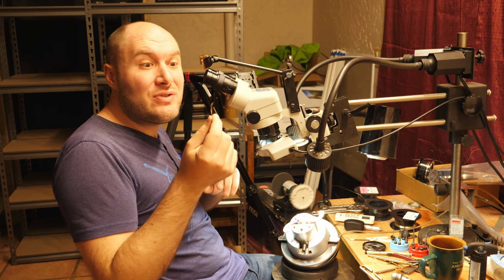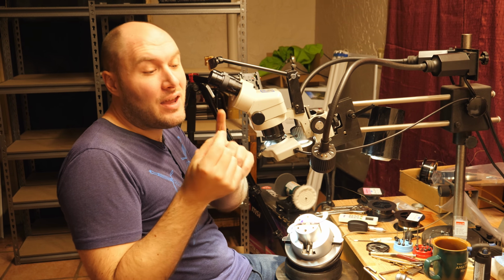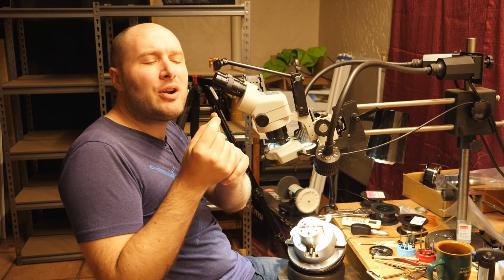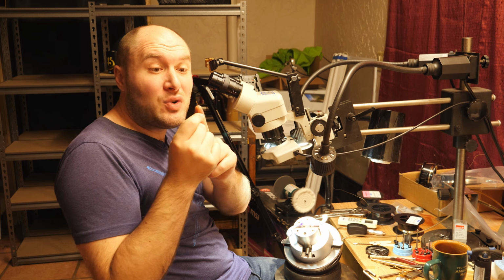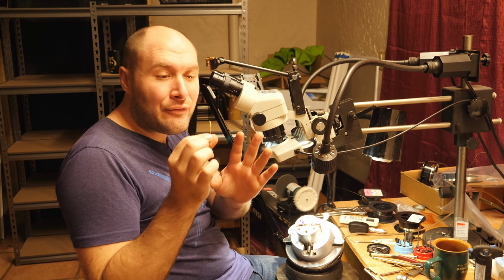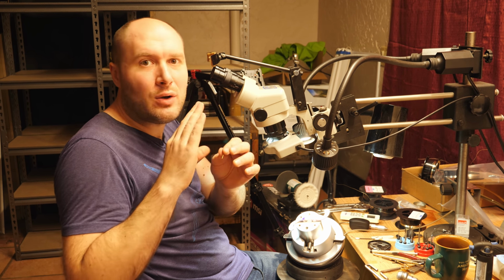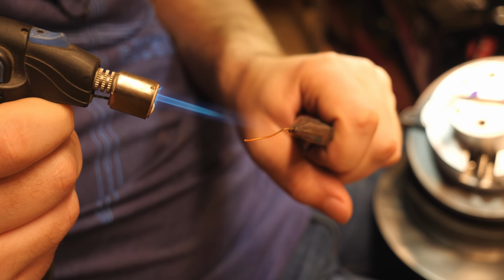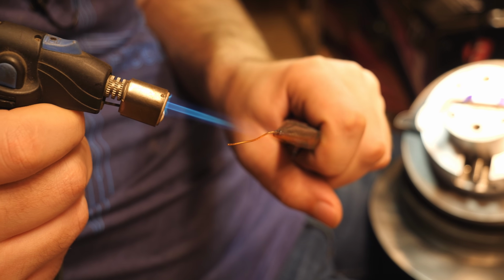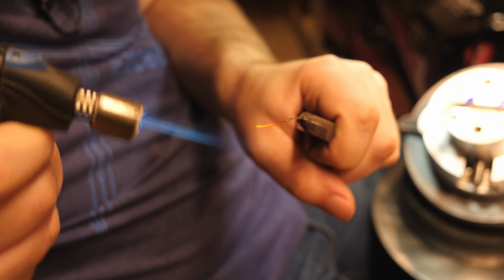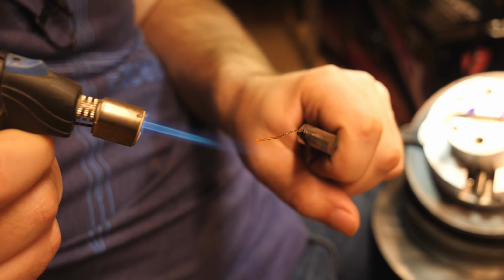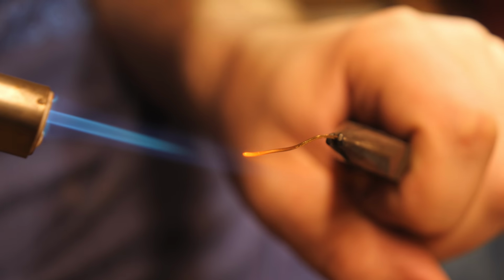The next thing we're gonna use is some really thick 32 thousandths diameter gold wire. This is 24 karat. I need to anneal it first to make sure it's nice and soft. We want the gold as soft as we can get it so it'll squish into the groove easier. And I also need to make a little tiny ball on the end. Just by melting it, it'll give me a little bit more material for when the wires meet up with each other. I'll be able to blend that seam in and make it invisible.